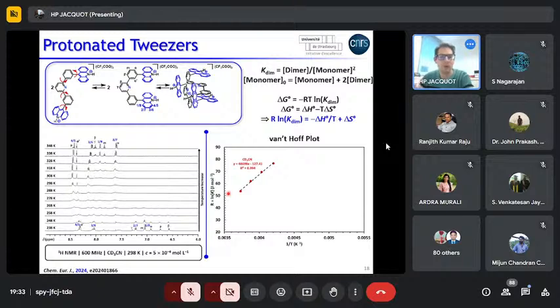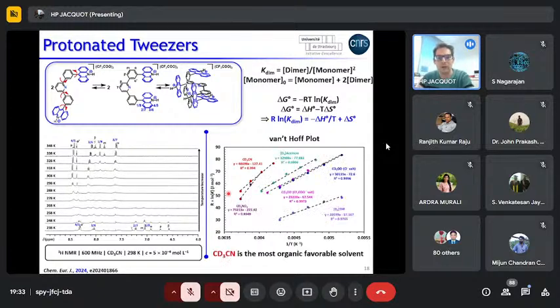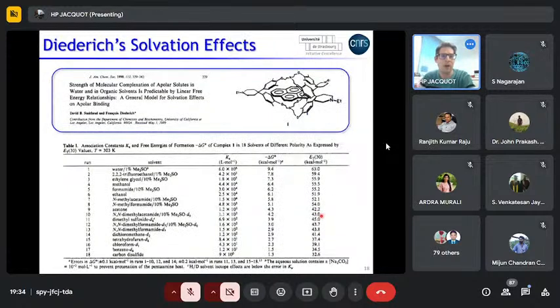What you can do in one solvent, you can do in other solvents. So we tried a bunch of them. What this graph tells you is that if you go on the left part, you will favor the association. And this goes with increasing the polarity of the solvent. And this is verified for almost all solvents except methanol. So this was a bit surprising to us, more especially when you know a little bit your literature.